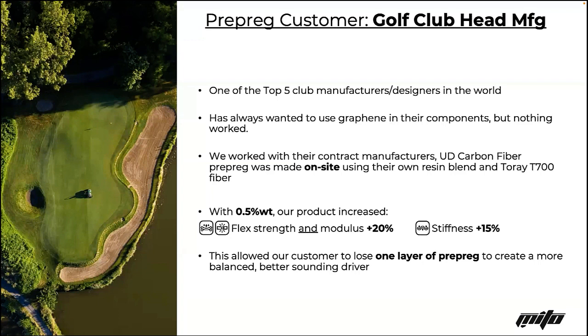And what they found is that with 0.5% by weight, the product increased flex strength and modulus by 20%, as well as stiffness by 15%. So again, this allowed them to go back to the drawing board and use less carbon fiber and less resin, which allowed them to redistribute that weight, but also to save some greenhouse footprint, because carbon fiber is one of the most greenhouse-intensive products in the world. And that's 10% of that weight. So if you're taking out 10% of that, you're saving 10% of your greenhouse emissions.